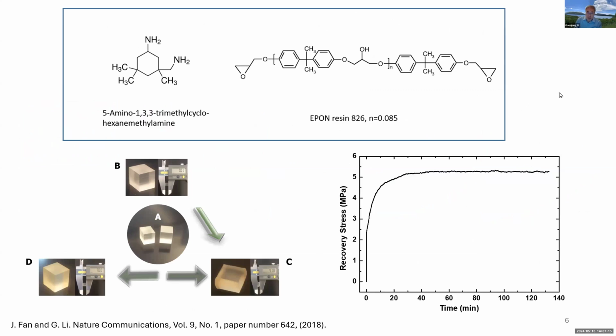Then we started to make new polymer networks. Here, I show you one of them. Basically, this cross-linker and this monomer, when they have these chemical cross-links, will be able to make a new thermoset shape memory polymer. And here we are showing the recovery stress testing. You can see that after about 6% of tensile programming, or tensile pre-stressing, we will have about 5 MPa recovery stress. If you just depend on the entropy storage, this stress will usually be less than 1 MPa.